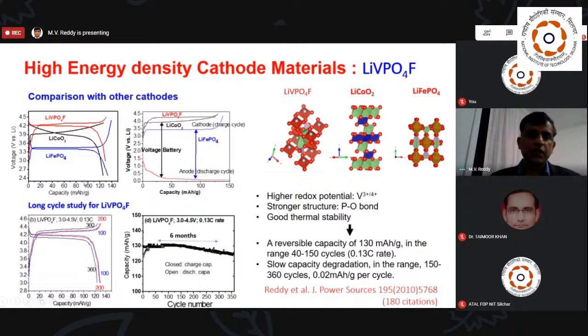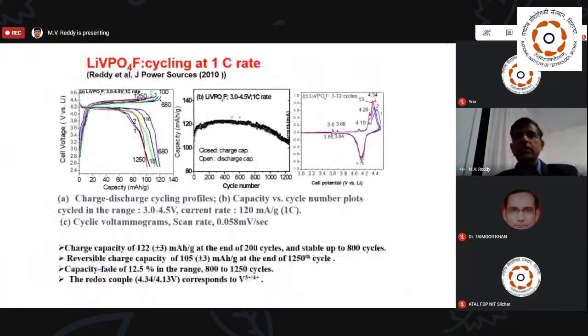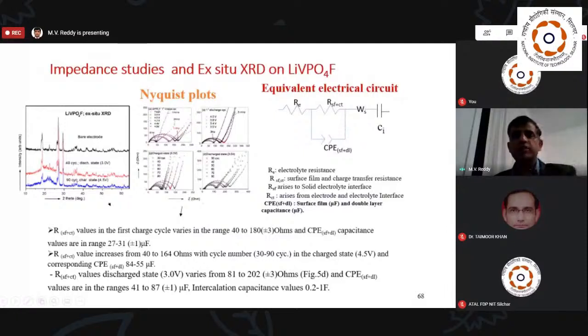And interestingly, this vanadium-containing compound gives nearly 4.1 volts. As I told you, higher voltage means higher energy density. So that is good for electrical applications or high energy density applications. Again, we can do this with higher current rates, etc. And these are the reversible charge-discharge curves, what electrical engineers call IV curves. And we can do some complex impedance.